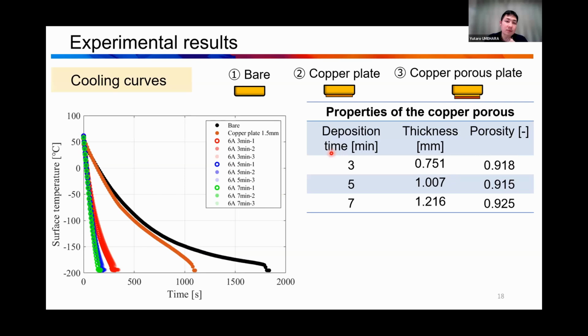So here is an experimental result, temperature versus time, and the bare surface case is like this. We spent almost 30 minutes cooling down to the saturation temperature of liquid nitrogen. Next one is here. This one is a copper plate. We just added a copper plate. The thickness is 1.5 millimeters, and it's like this. In this case, we can reduce the cooling time by 40%.